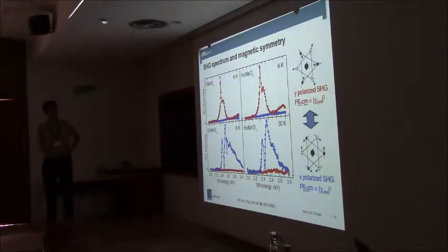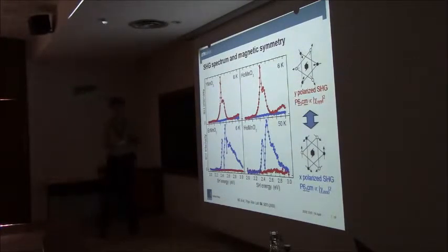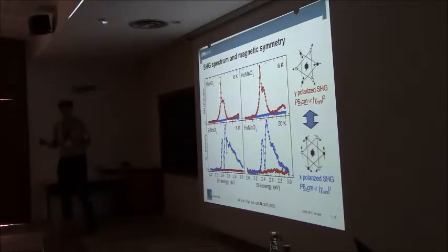Holmium manganite is an interesting case. At 50 Kelvin, it's this spin structure. At 6 Kelvin, it's that spin structure. And that's it. So you have answered this 4-decade-long question with no ambiguity at all left.